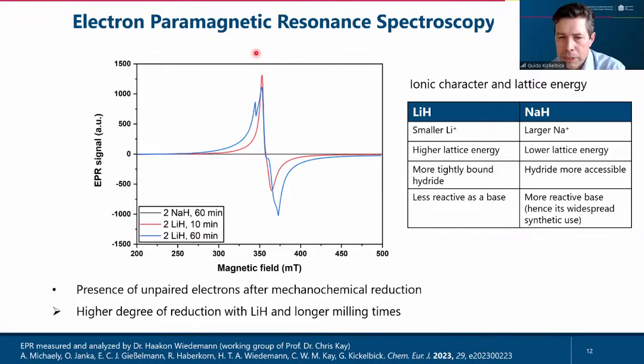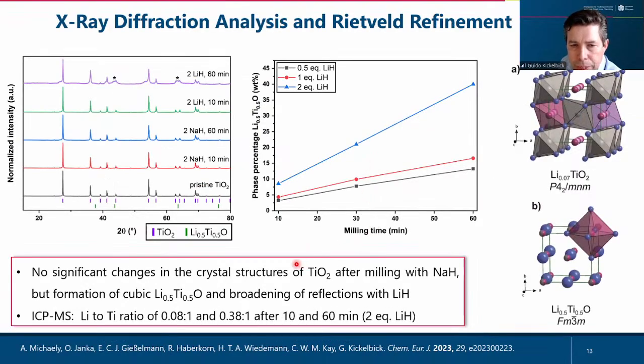And this is a little bit counterintuitive concerning the chemistry of the hydrides. I put the general knowledge about the comparison of lithium and sodium hydride on the right-hand side. Lithium has a smaller ion, has a higher lattice energy, has the more tightly bound hydride, and therefore is the less reactive hydride. However, in our experiments, we saw that lithium hydride has a higher potential to reduce titanium. So the question was now, why is this the case? We figured that out by Rietveld refinement.